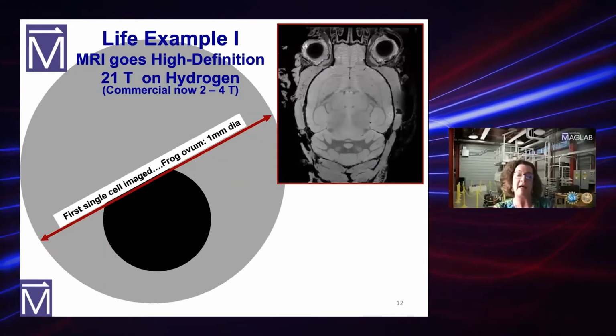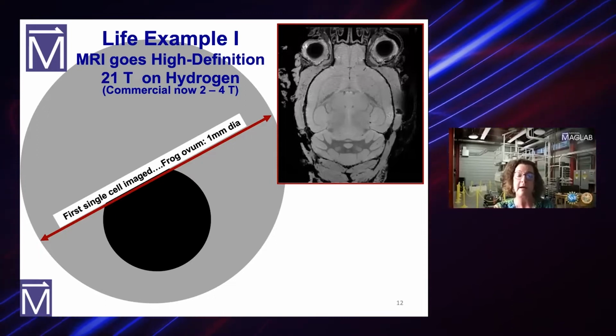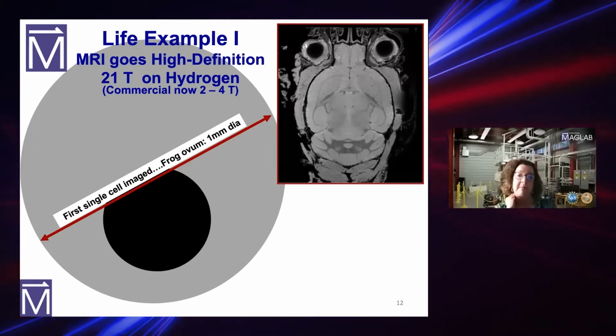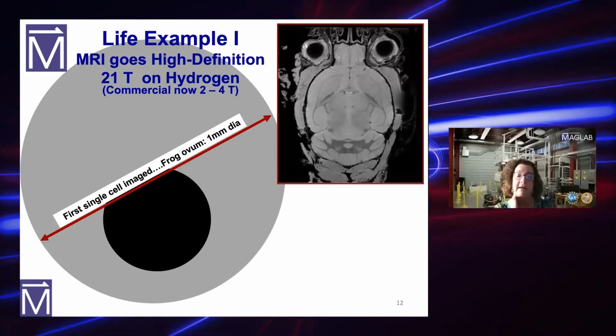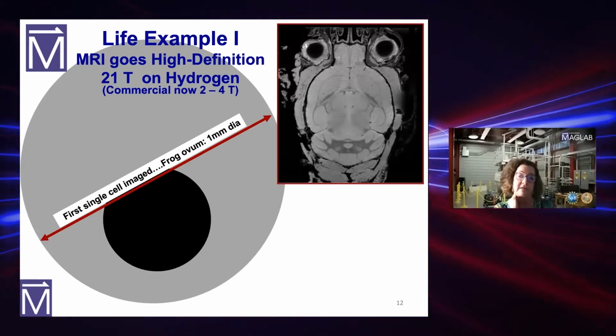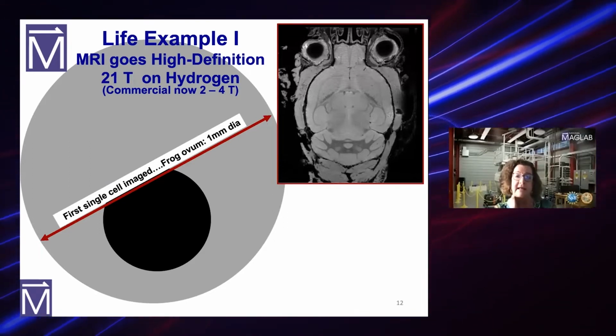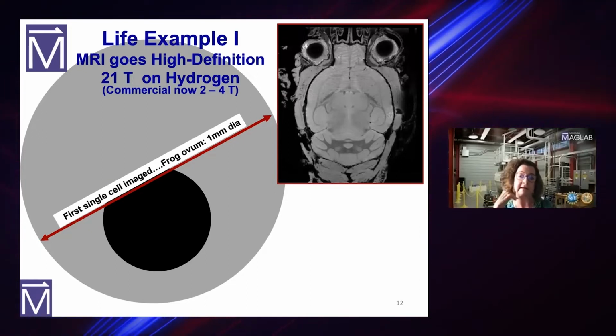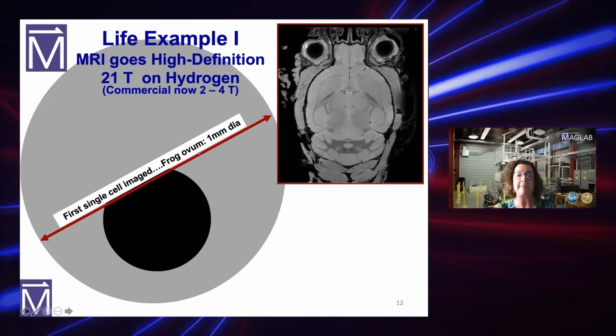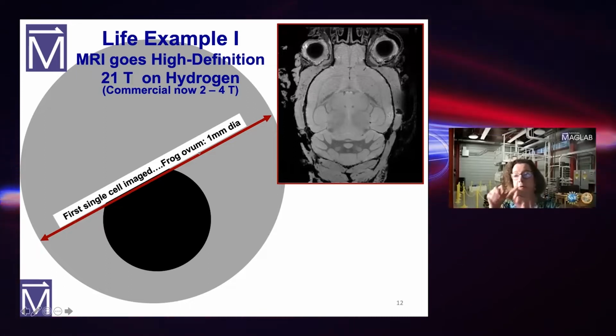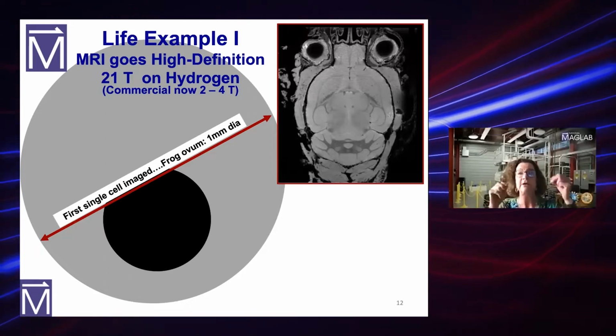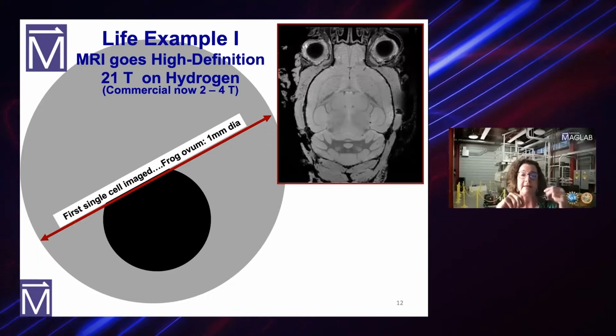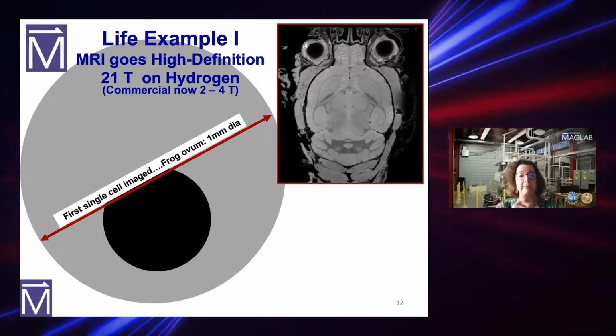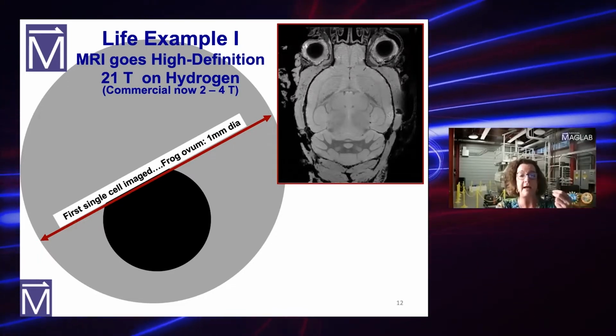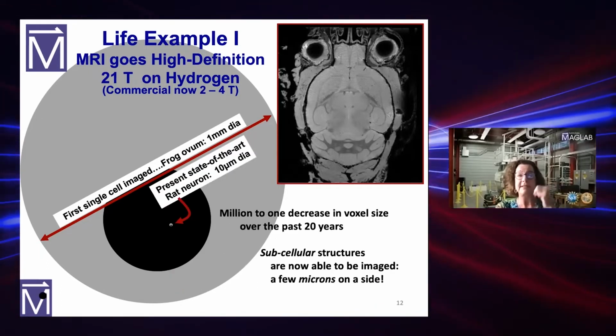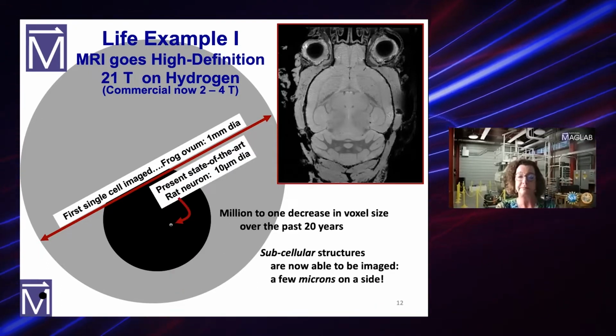One example of life is high resolution MRI. So probably most of us have had MRIs, and in the commercial MRI, you go in and this is 2 to 4 Tesla. Now this is an example of a single cell image. You have about 1 millimeter diameter. If you're imaging like we normally do when we do MRI in a hospital, you image on the hydrogen. And then we get about a 1 millimeter diameter. But if you image the hydrogen at 21 Tesla, you get to 10 microns resolution.